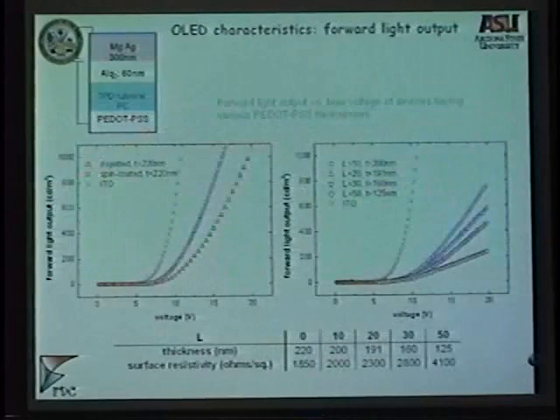So we made the OLED. We spin-coated the PEDOT:PSS, and on other substrates we inkjet printed the PEDOT:PSS, and then deposited TPD with rubrene for yellow emission, then Alq3 for electron transport, and the final thickness of 300 nanometers for magnesium silver as a cathode. And on some substrates we had ITO, no PEDOT, and built the same structure just for comparison.